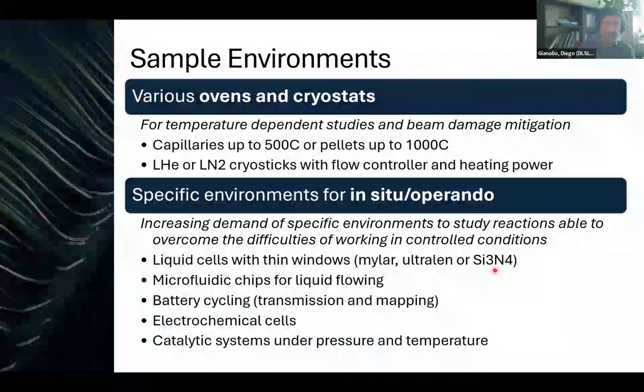One, again, for the same reason that I explained before, all the materials that you are using that could intercept the beam would affect the measurement. So the windows need to be thin, and they need to not contain any element that could be in the energy range of interest. Discussing with the other people in the group that work in tender X-ray beamlines, we came across, well, I think that the two most common sample environments are ovens and cryostats that allow for temperature-dependent studies. And in the case of cryostat, they also help with beam damage mitigation.